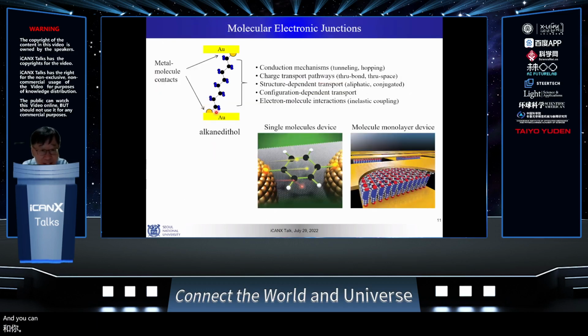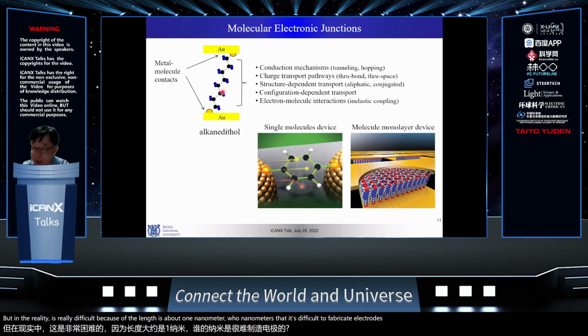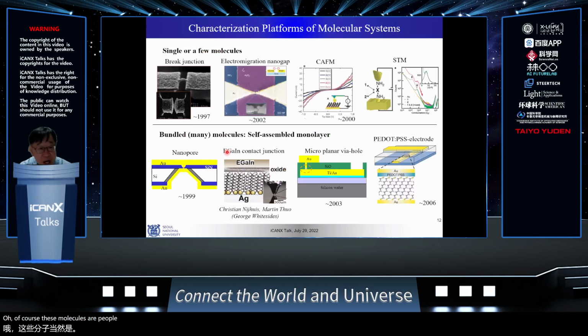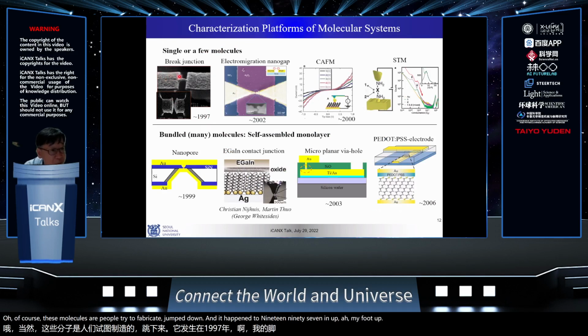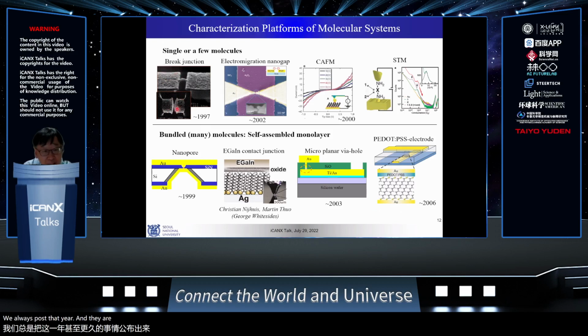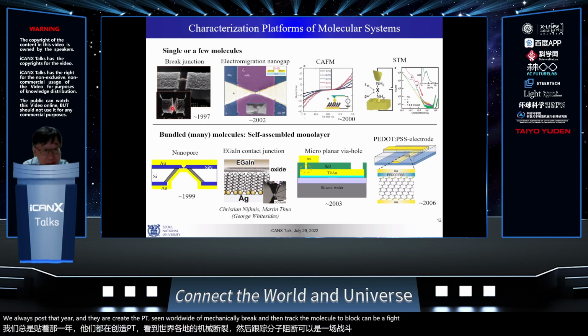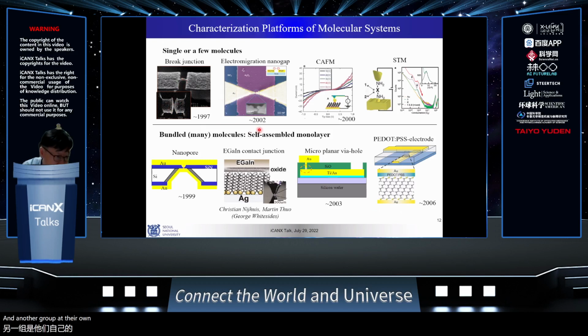And you can imagine it looks easy to draw in PowerPoint, but in reality it's really difficult, because the length is about 1 or 2 nanometers, so it's difficult to fabricate an electrode across this molecule. People tried to fabricate junctions, and in 1997, when I was a postdoc at Yale, they created a very thin gold wire that was mechanically broken, and then trapped the molecule at the broken site. Another group at Cornell and Harvard made a pattern and then flowed high current, creating a nanogap by Joule heating. They call it the electromigration nanogap.